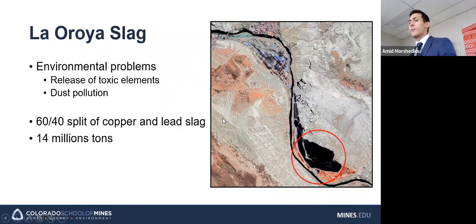So where did the slag come from? Well, they are a polymetallic facility, and two of their primary products are copper and lead. So this particular slag pile is a 60-40 split between copper slag and lead slag. The copper slag is from their copper reverb furnaces, and the lead slag is from their blast furnaces. There's about 14 million tons of this stuff, and so that begs the question, what's in the slag?